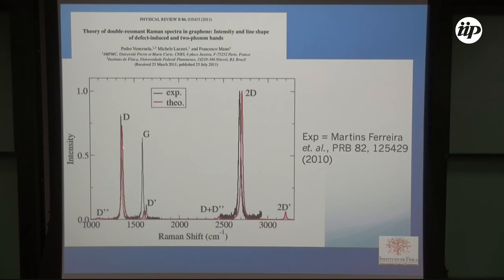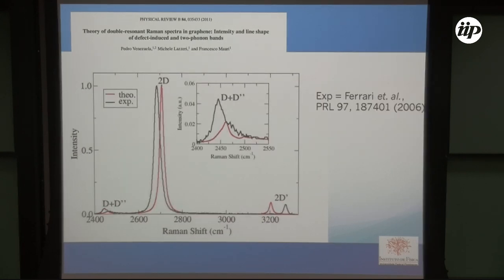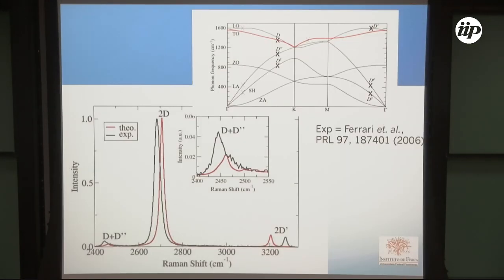And here we have another, when we compare the intensity of those defect peaks with the two phonon peaks, we have one adjustment parameter, which is how much the hopping parameter changes when you put a defect. So we have here just one parameter to fit the relative intensity of this peak with this. We also compared our results with Andrea Ferrari's paper. Here I want to call your attention, because, for instance, the 2D peak, in our calculation and the measurements, is very symmetric. It's very close to a Lorentzian. But for the other one, it's not symmetric, for the calculation or for the experiment. So we have a very, very good agreement also. However, okay, later I'll come back here.